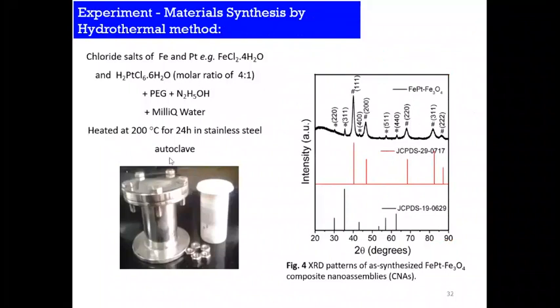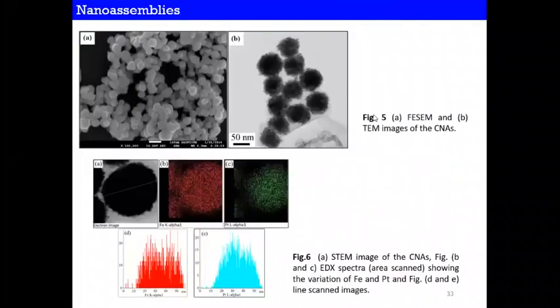And we have tried a hydrothermal method using H2PtCl6, chloroplatinic acid, and iron chloride, and you can see that it is synthesized at 200 degrees centigrade. From the XRD pattern there is clearly iron oxide and iron platinum, and it forms the nanomaterial like this. This forms through a self-assembly technique.